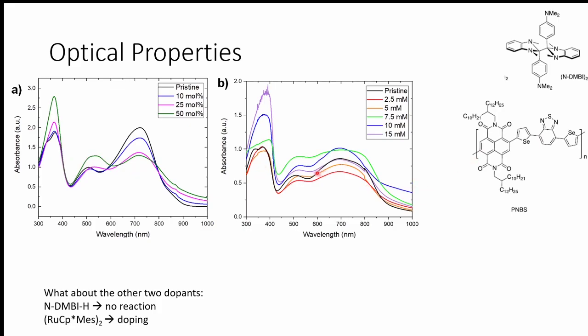Now, in the solid state, because there are a lot of aggregates being formed, it's not as easy. But here, this absorption in the UV area is where the dopant ion absorbs. So as we use a higher concentration of the dopant solution we're dipping in, we're getting a higher absorption. So we know there is incorporation going in, and we have slight changes in the absorption spectra. So we know there are changes.